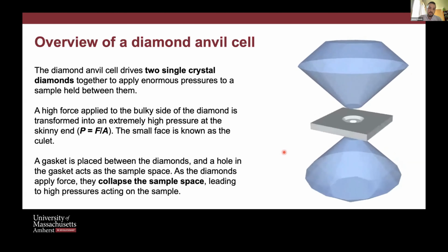So instead we use a gasket material, which really makes up the walls of the sample space. All this boils down even further into just the sample space, which is a cylindrical void that we put the sample into. As we drive the diamonds together with whatever force applying system, whether that's screws or a gas membrane or piezo, what we're actually doing is collapsing that void. As we do that, the pressure increases through the pressure transmitting medium, which fills up all the spaces, and then that pressure gets applied to the sample.